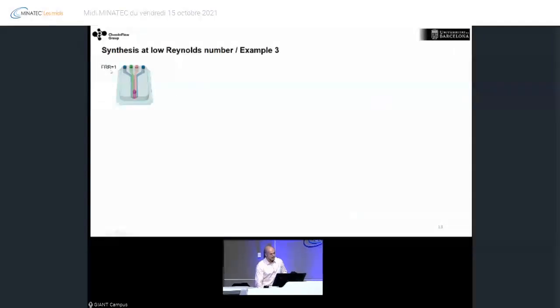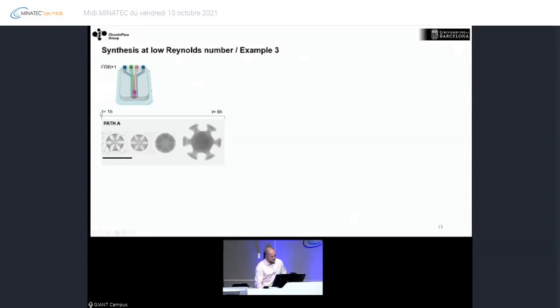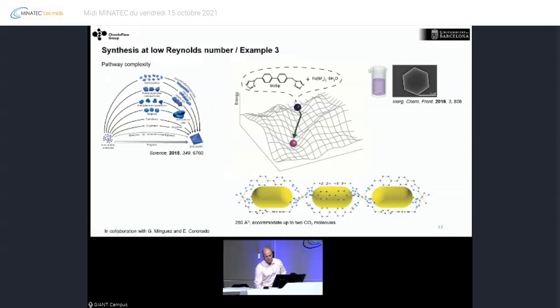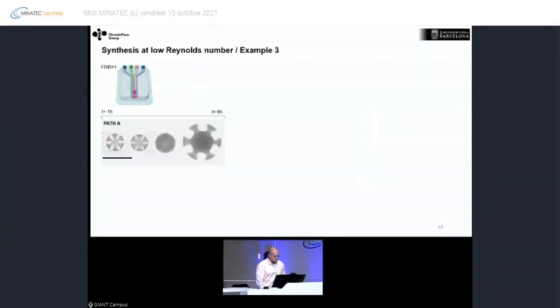Now here we fix the flow rate, and what we observe is that from 0 to 6 hours, we have this kind of crystal growth, with the formation of the hexagon. Let me show you that if you do the reaction in bulk, you have this hexagon as a thermodynamic product. When we do the reaction with microfluidics, we also have a hexagon, but this hexagon is growing from the vertices of the inner one.